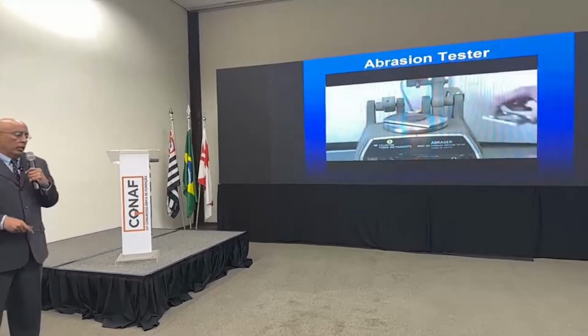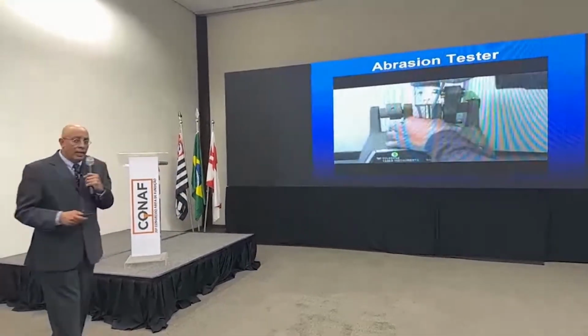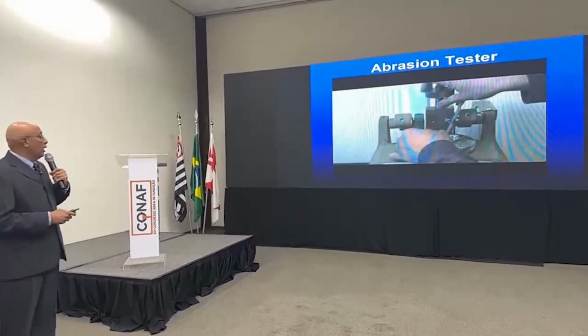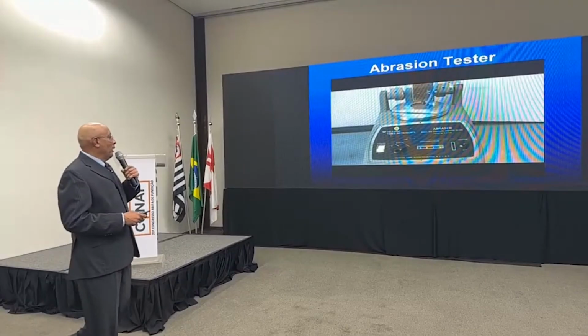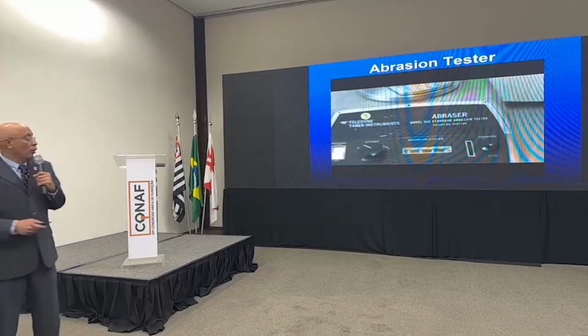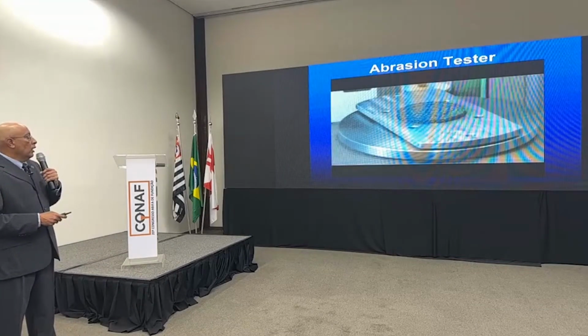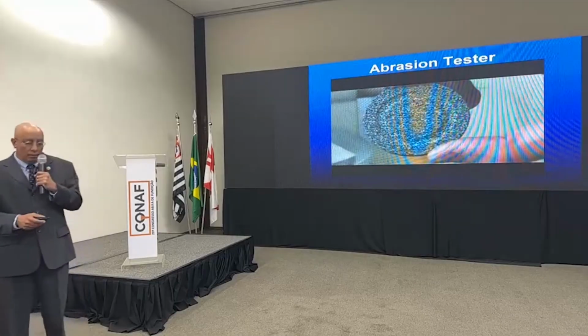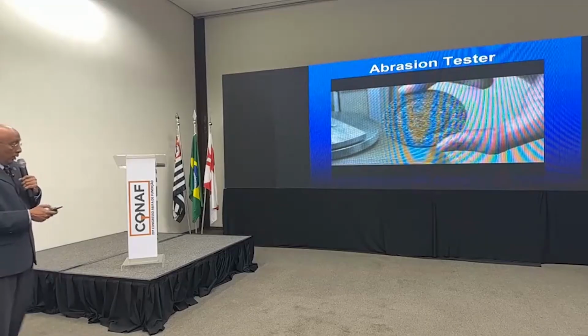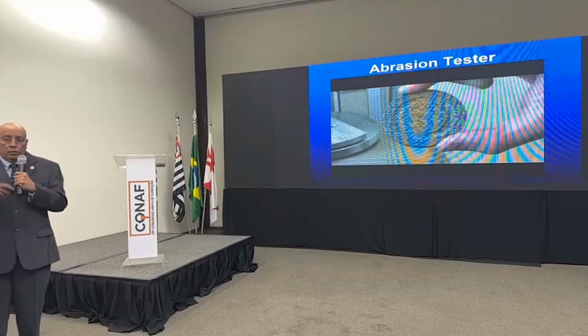This is the one that tells us about the level of cure in the sand or the friability of the chemical binder system. It's a ceramic ball that is 4 millimeters rotating against the specimen at a predetermined load for 20 rotations. And we look at either the depth of penetration or the losses of sand as a percent. That is the function of the friable losses from abrasion. It's representing the molten metal flowing past the chemically bonded sand.